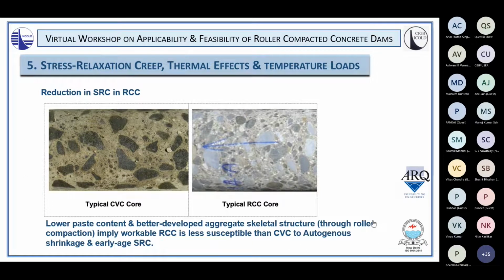And now if we look at stress relaxation creep in relation to roller-compacted concrete, in terms of the structure of the concrete, and particularly a higher workability RCC, the process of compaction under roller action really involves squeezing the aggregate skeletal structure together and releasing paste up to the surface. And this results in a very different skeletal structure compared to conventional mass concrete. One picture that I use to describe this difference is imagining conventional concrete as aggregate in a soup of paste, whereas RCC is a skeletal structure of aggregates with paste in between.